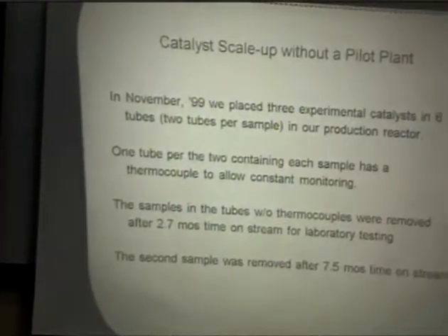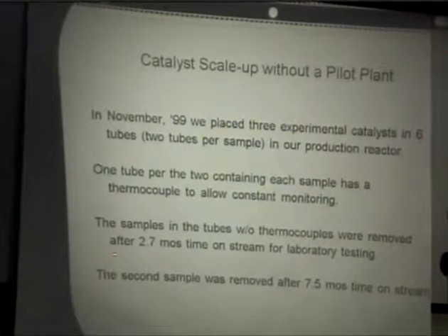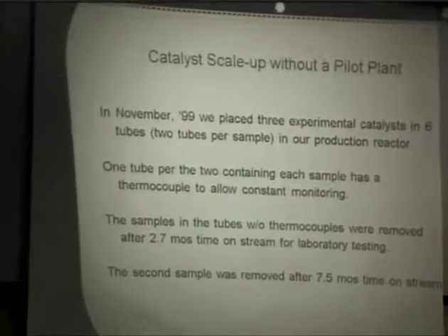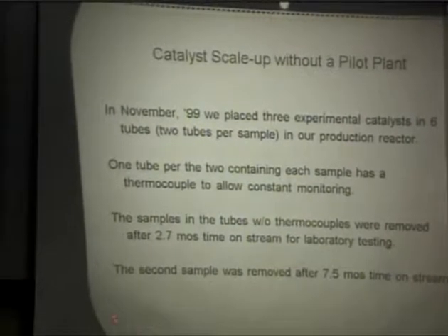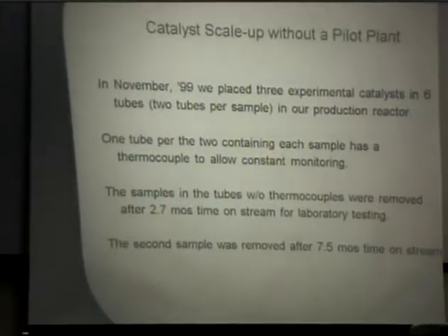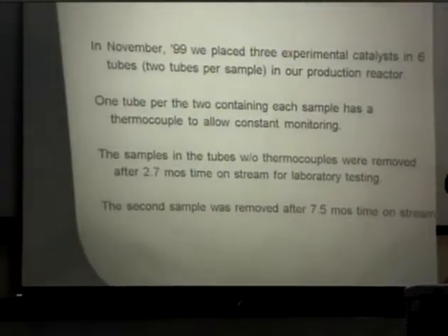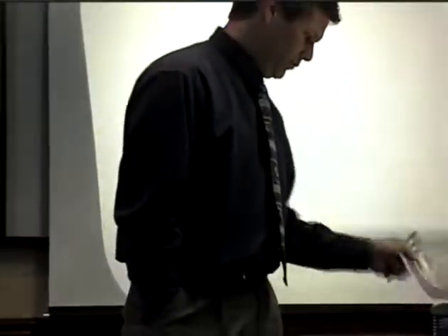One of the tubes contained a thermocouple, and that allowed us to monitor the temperature. The second tube was just a catalyst, and we removed that material after 2.5 months time on stream. Then the second sample was removed after about 7.5 months time on stream to get us a feel for how it was performing with time on stream.